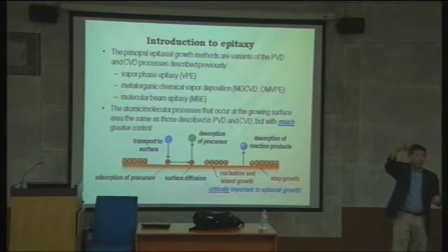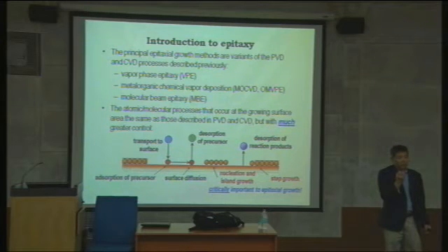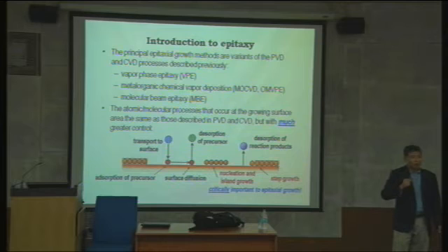Because of the atoms coming down to the surface, there is some energy, and this energy has many different types. One is thermal energy, because the temperature of your source is very high, but the thermal energy is very small. That's why evaporation or MBE is a much more gentle process, because the energy is only less than a few eV. It's a very, very small energy. In contrast, sputtering uses very high energy acceleration of argon ions. When you knock out these atoms or ions, they sometimes have very high energy, because the ion energy ranges from 50 to sometimes 200-300 eV, which is very high. Otherwise, you cannot knock them out.